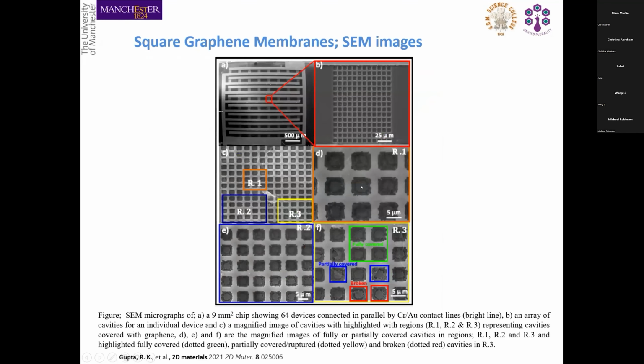surface. So this shows an SEM image where you have this 9 millimeter square chip. This is a 9 millimeter square chip at the moment, but it can easily be 1 millimeter square because lithographically it's all possible. And then you see an individual device. There are again the same cavities in silicon oxide and graphene on top of it. In the SEM images, where you see a bright portion, that's just charging, which means there's no graphene. And there are some areas where you see the graphene.